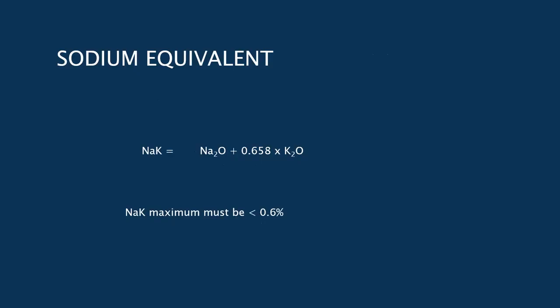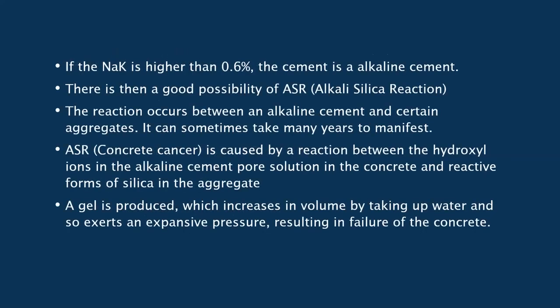Here, it's a very important thing. Your maximum cannot be higher than 0.6%. If the NaK is higher than 0.6%, then you start getting into an alkaline cement. And as soon as you get into an alkaline cement, there's a good possibility of something called ASR, alkali silica reaction. And this reaction occurs between alkaline cement and certain aggregates, not all of them, certain aggregates. And it can take sometimes 15 to 20 years to manifest.